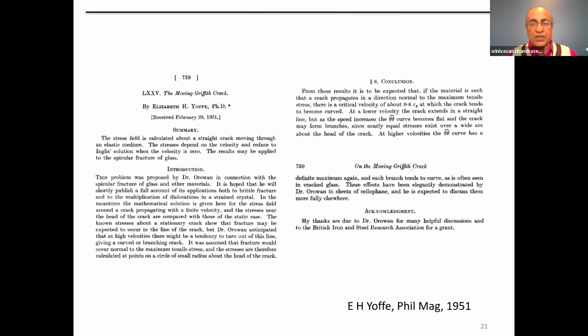And then Elizabeth Yoffe went and showed that there is crack bifurcation, and she explained why a crack would bifurcate as the speed increases. It turns out that cracks try to run perpendicular to tensile stresses. So if you pull, a crack will always propagate perpendicular to the pull. It turns out when a crack picks up speed, at a certain speed, just ahead of the crack, it sees very many directions in which the tensile pull is equalized. So it's like coming at a fork in the road, and there are 10 forks, and you can choose to go whichever way you want because all are equally easy to run along energetically. And so the crack is given an option. It picks up speed, and suddenly it finds that it can go in 10 different directions because the pull is equally good in all of those directions. And that manifests as crack bifurcation.